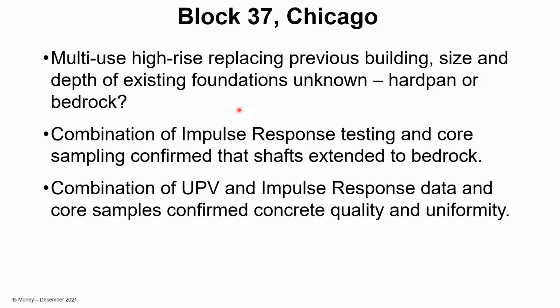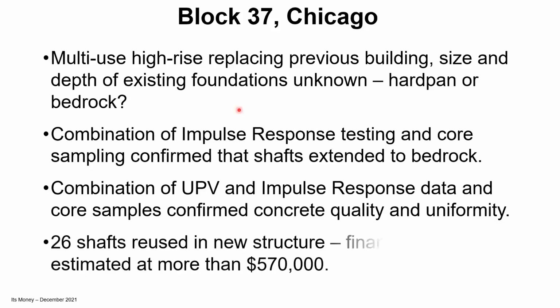A combination of ultrasonic pulse velocity testing horizontally through the top of the shaft and the impulse response data estimated the depths. The UPV data enabled us to come up with a velocity for the impulse response data, and so refine our estimate of shaft depth, which correlated with the core samples and the bedrock depth. So again, a high degree of confidence the shafts were rock on top of rock. In total, 26 shafts were used in the new structure there, with a financial saving of more than $570,000.